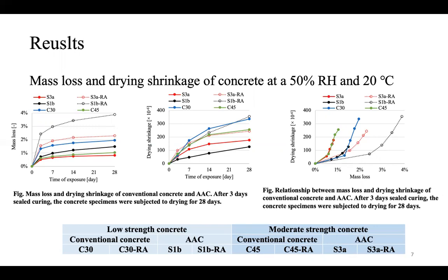The main reason is the higher amount of alkali activators used in moderate strength concrete, because more alkali activator may result in a finer pore structure. In the finer pore structure, high tensile stress may develop under drying.